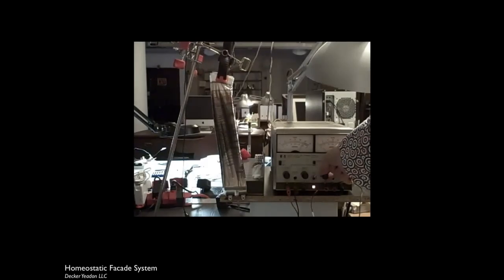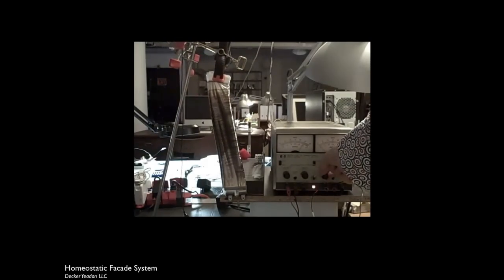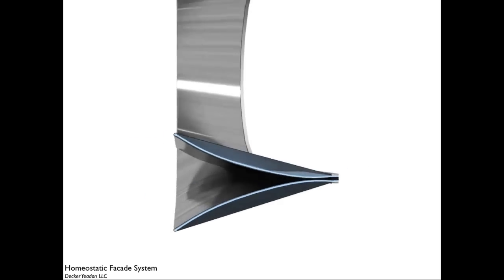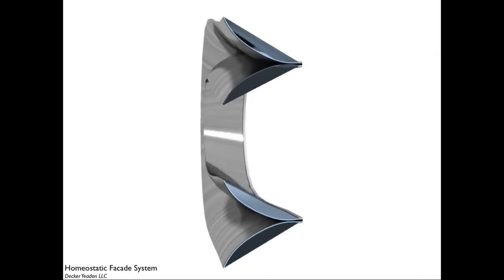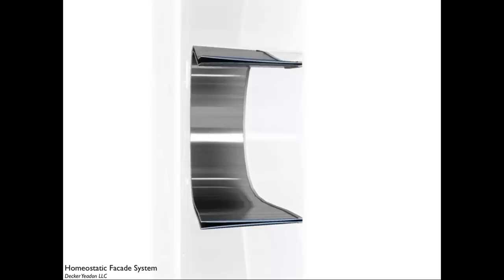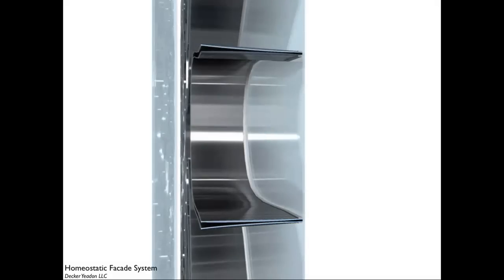As you can see here, as soon as you apply a high voltage to the electrodes, the movement is not as big as you would want it to be. There's still a fair bit of research to be done. Nevertheless, we designed an actuator that would work with minimal movement. What you see here in light blue is a flexible core that is wrapped in that silver muscle that can, depending on how you apply the voltage, open and close again to control solar heat gain in buildings.